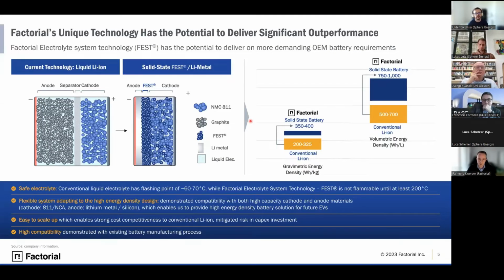So from an energy density standpoint, you do not only increase the volumetric, but also the gravimetric energy density quite significantly. And in respects of safety, it's very important to mention the thermal improvement. So when you compare conventional lithium-ion batteries, you use something like ethylene carbonate, which has a flashing point of maybe 15, 17 degrees. And then you add a couple of flame retardants to eventually reach 60 or 70 degrees for flaming point. So our technology is thermally stable up to 200 degrees, which might not sound like a lot, but it's a huge improvement from automotive point of view.